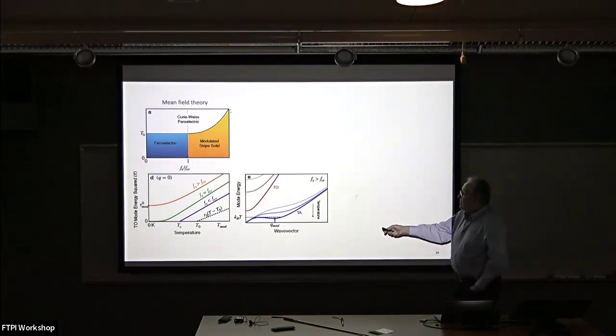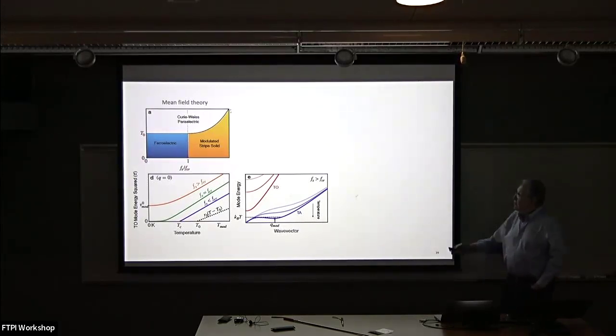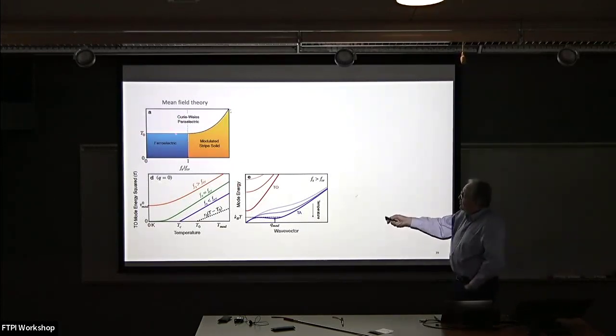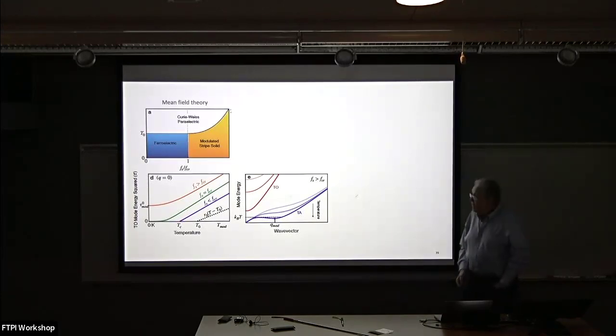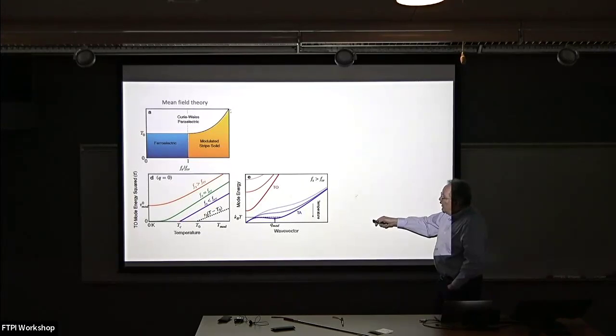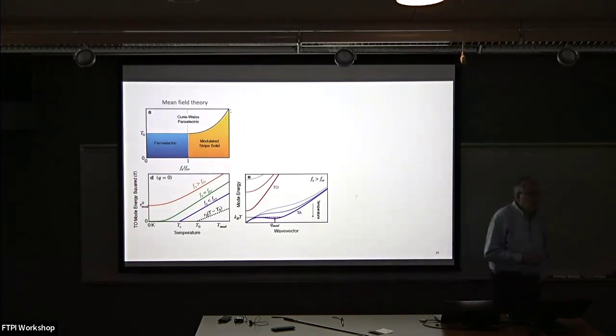So it starts with 0, there's some critical coupling. And that critical coupling at the mean field level is just associated with when you come down here, so now we're looking at the TO mode frequency. If the critical coupling was too small, all that happens is the TO mode frequency goes through 0. I get this line. And then if it's big enough, what happens is that the TO mode frequency doesn't go soft anymore, but instead q goes soft, so modulated phase. And I would get a stripe phase. That's all there is at the level of Landau theory.